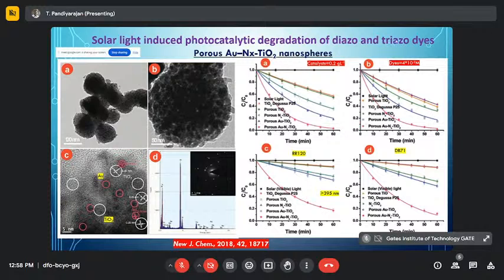And if you look at the data, this black color, that is where we have used only solar light without use of any nanomaterial. So without use of any nanomaterial, there is almost no degradation. The degradation is zero. But after usage of titanium dioxide, this particular violet curve, that is just titanium dioxide which we purchased directly from the market. Okay, it is not nanomaterial. That has a very low percentage of degradation.